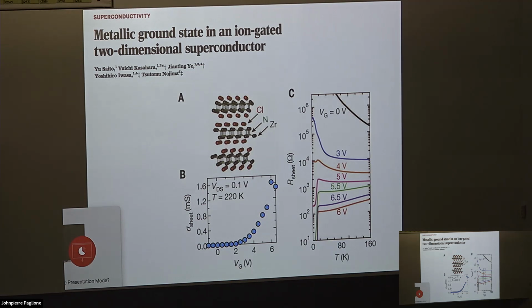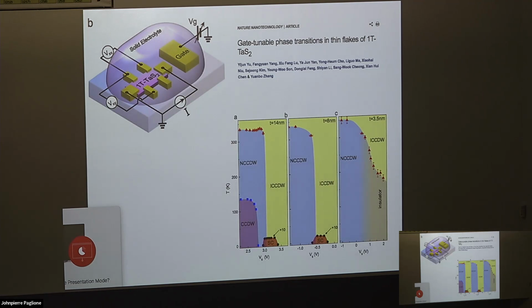And so this was used to produce some superconductors. And you can change the behavior based on the gate voltage. Essentially, you're gating the carrier concentration. So that was very interesting. They made a device out of tantalum disulfide, and they could change the phase diagram based on the gate voltage. And that was kind of cool.